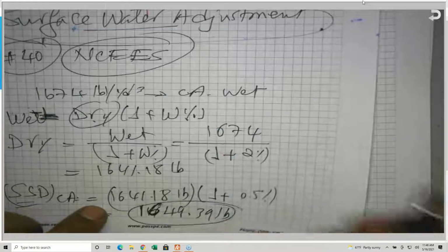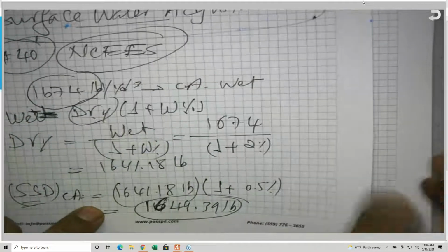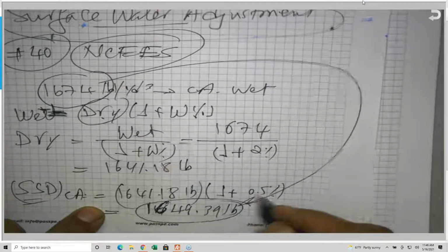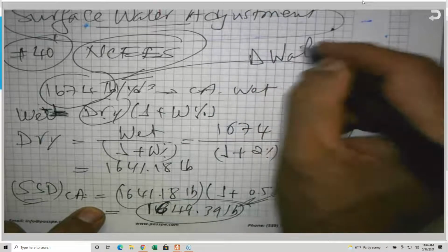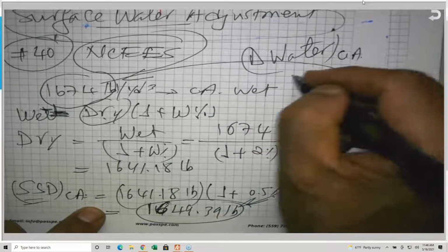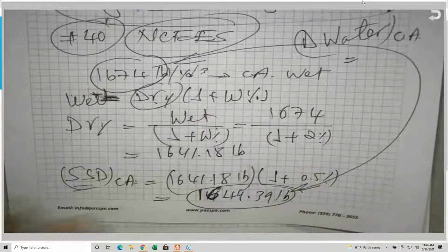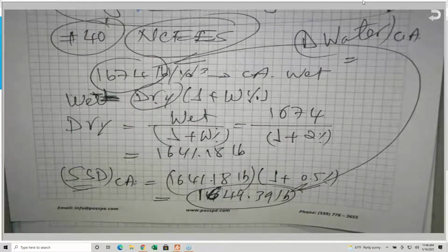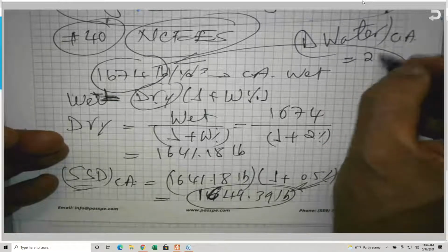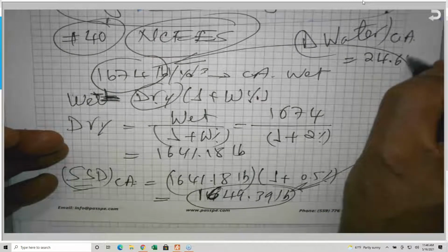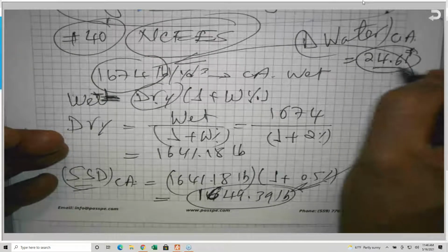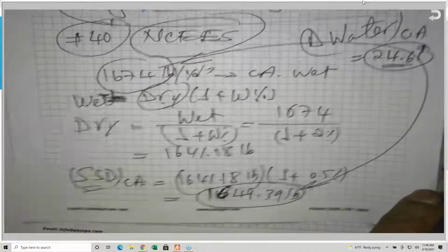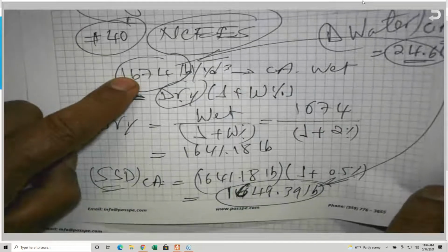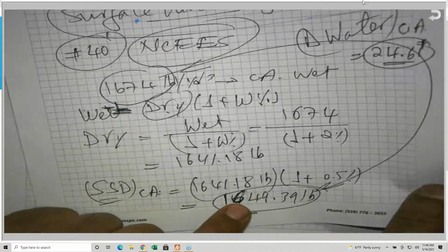What he did, what he put was 1674. How much difference between this and this? This is how much delta water for the coarse aggregate, which if you take this number 1674 minus 1649.39 equal, that means there is 24.61 pounds extra water. I dump this, but it is wet. I need to keep this only, the rest will be excess water.